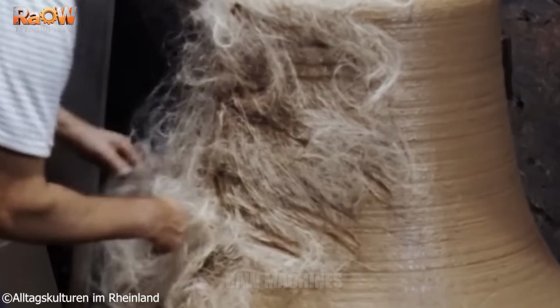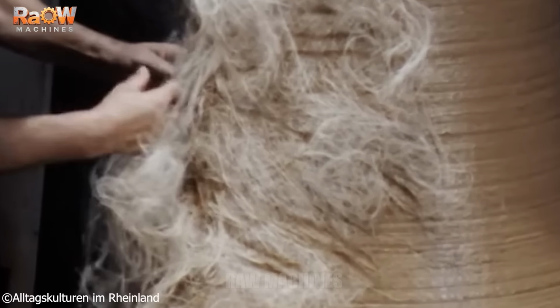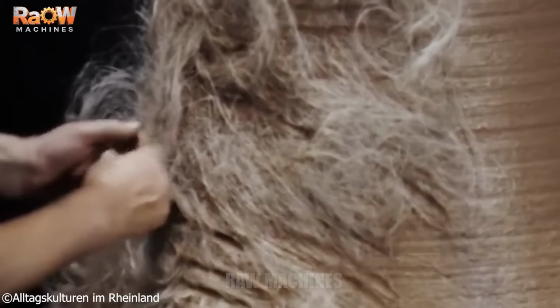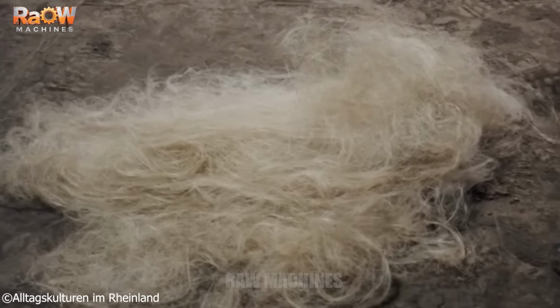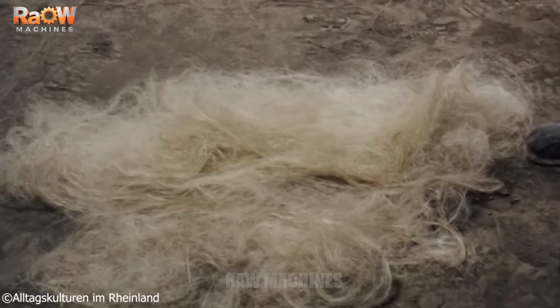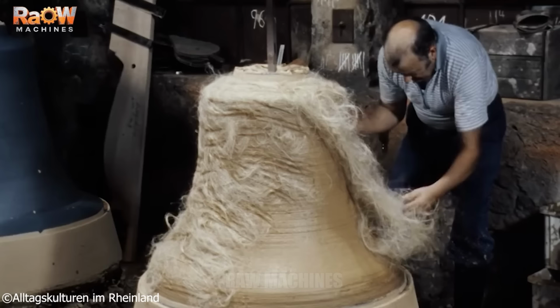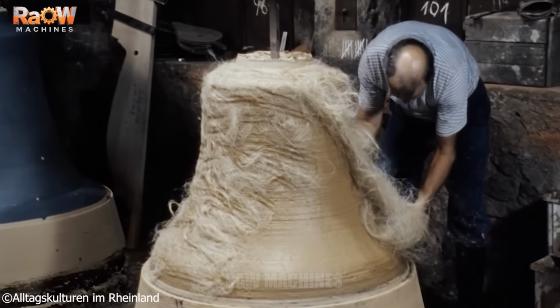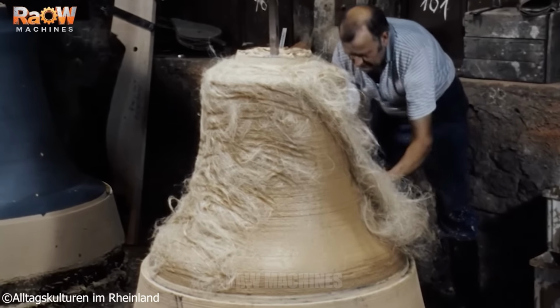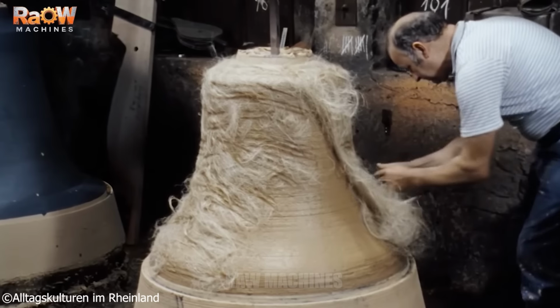Over a period of 4 weeks, the mold makers apply successive thin clay layers reinforced with jute fibers until the false bell reaches the exact wall thickness of the final bell. At this point, the second component of the casting mold is complete, ready for the subsequent stages of the process.